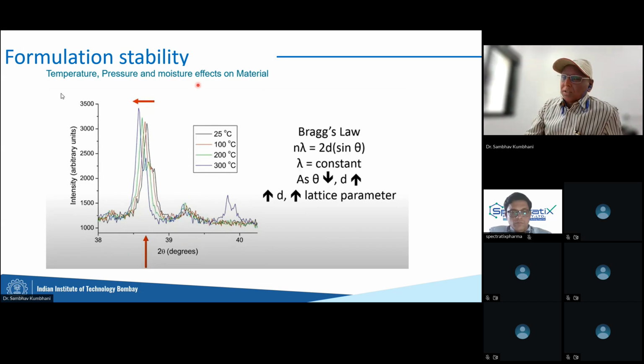A lot of pharma companies measure the moisture effect, like going from 1% relative humidity to 99% relative humidity. Why do they do that? Because they want to ensure that the tablet is stable in the Sahara Desert with less than 5% humidity, and is stable in Mumbai with 80% humidity. So that study is very important, and they do this with similar kinds of spectra.